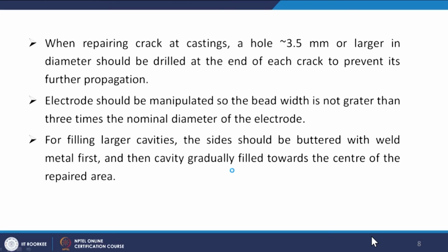When repairing a crack in a casting, a hole of 3.5 mm or larger diameter should be drilled at the end of each crack to prevent its further propagation. Electrodes should be manipulated so that bead width is not greater than 3 times the nominal diameter of the electrode. For filling large cavities, the side should be buttered with weld metal first, then the cavity gradually filled towards the center of the repaired area.